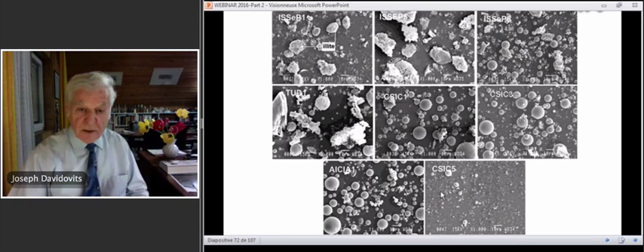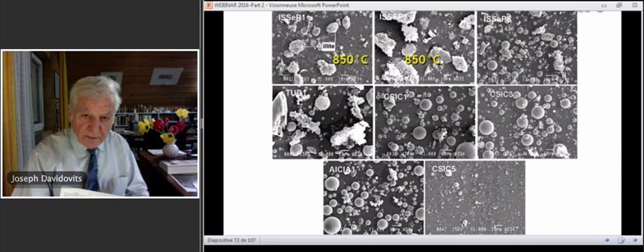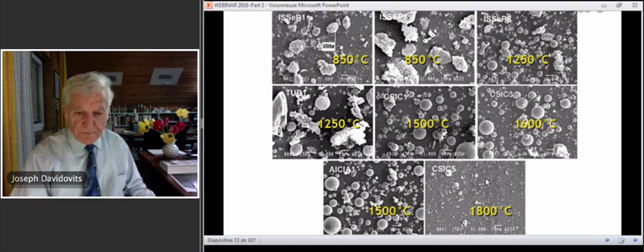If we look at the electron microscope, this is 850 degrees C, you have the remains of the clays here. At 850 degrees C, this is the remains of kaolin, this is a characteristic shape. At 1250 degrees C, we start to have good spheres. At 1250 degrees C, we have remains of biomass here. At 1500 degrees C, these are the ideal fly ashes. At 1400 and 1800 degrees C, these are power plants that are working on a totally different system. They are first getting, this is a gasification of coal.